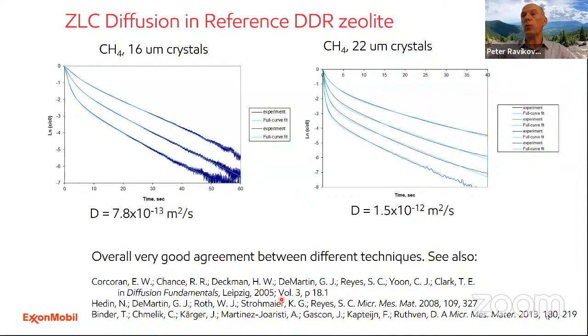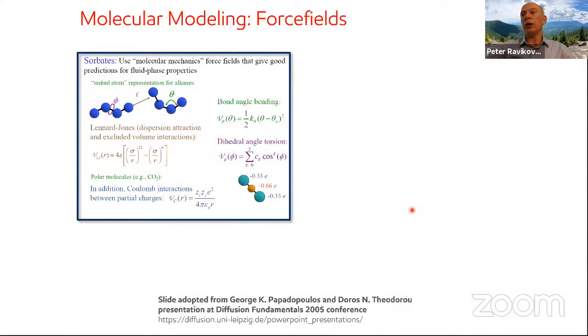Here is some literature where other methods were used to study diffusion in DDR crystals using membrane measurements, using PFG NMR, using infrared microscopy methods, and all of them show the same results, about 10⁻¹² meters squared per second. So it's a good reference system. Now, how do we do molecular simulation? I'm not going to give you a big lecture on molecular simulations. I would like to point out 2 wonderful lectures by Randy Snurr and others.